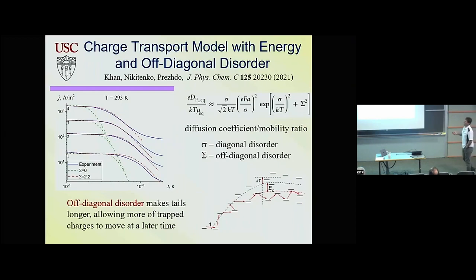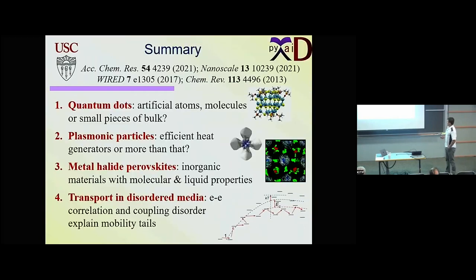If you have a simple, standard model, your tail of decay is very sharp. But if you introduce disorder, not just disorder in the energy levels, which is the standard model, but also disorder in the coupling between levels, then you can have a much better description of this tail. So for weak mobility, you have to advance the models of the type that Sasha Efros talked about to include correlations or some disorder, and then you can describe finer effects. And this is the end.